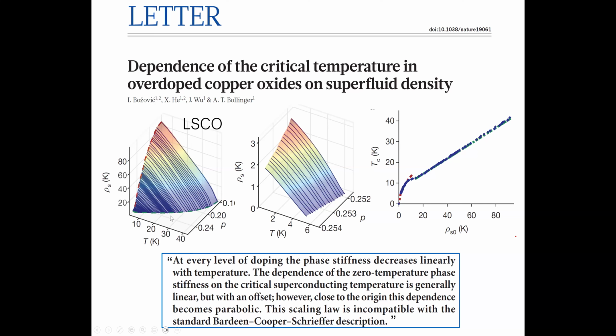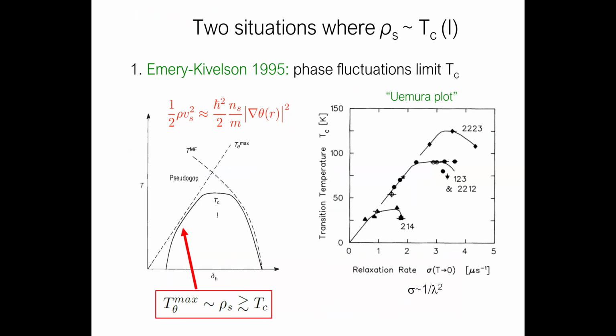You can see, first of all, that there is a superfluid density that decreases at the same time that T_c goes down on the overdoped side. And you can see that the temperature dependence of the superfluid density, or the penetration depth, if you like, is quasi-linear in temperature. So here's the plot of T_c versus ρ_s that Ivan produced in this Nature paper. So that's unexpected. In BCS theory, we expect the superfluid density to scale as the carrier density, which would be a fairly weak dependence here, and instead it's scaling with T_c.